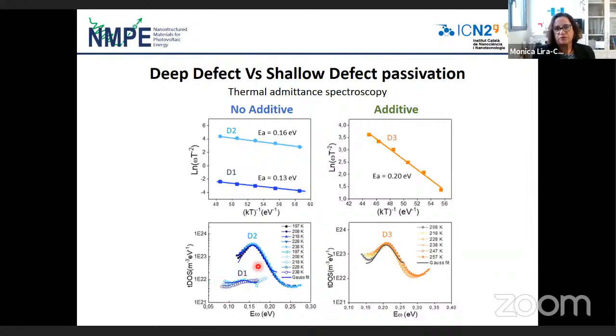So we have both types of defects with our reference device without additive. Once we add the additive, we see that we don't have any shallow defects here. That means that we are truly passivating shallow defects.